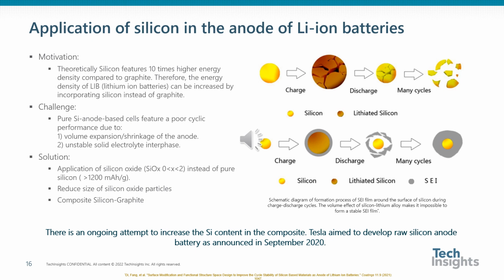The first one is the application of silicon oxide instead of pure silicon. Silicon oxide undergoes lower volume expansion during cycling than pure silicon, but still, it has 3 times higher capacity compared to graphite. The second approach is to synthesize silicon particles with smaller sizes, in fact going to nanoparticles, to alleviate the cracking issue. However, a promising method to develop a stable, high-capacity anode is taking advantage of the stability of the graphite and combining it with the high capacity of the silicon and silicon oxide-based materials to create a composite anode. Compared to graphite alone, hybrid materials possess a higher specific capacity and good cyclability and long-term stability.